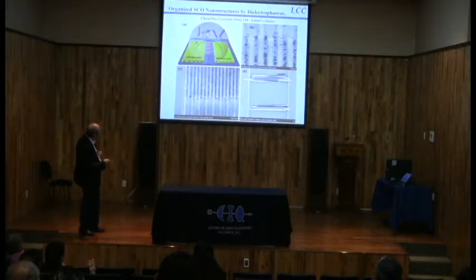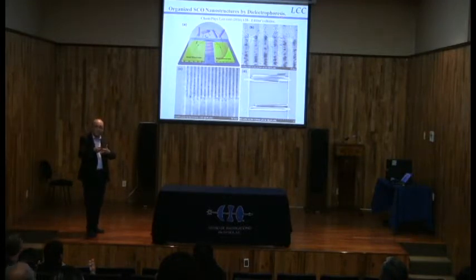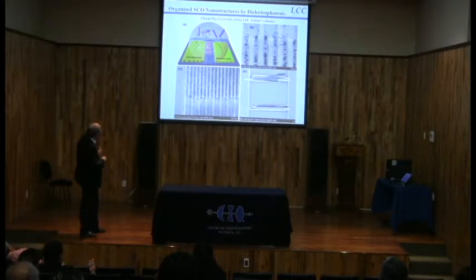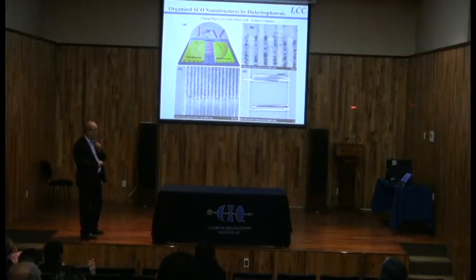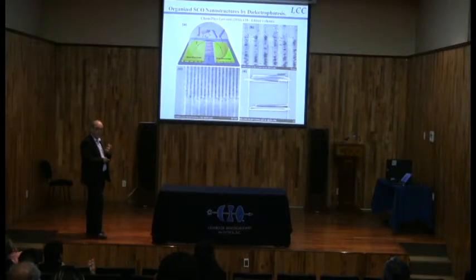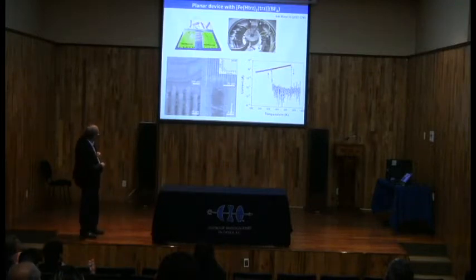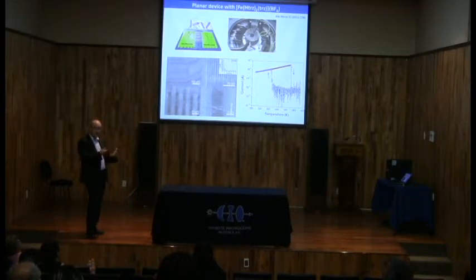If you take these rod systems, we can then, by using dielectrophoresis synthesis, that means that you do your synthesis in the presence of an electrical field, organize your rods between electrodes. If you do your protocol well, you can even select one nanorod here and measure the transport of your rod and the electrical properties. And then we did this, what you can see. You see, as a function of the current and temperature, you have a beautiful hysteresis loop here at room temperature of the current. That means that we can use the electrical properties of the systems for reading the information after integration.